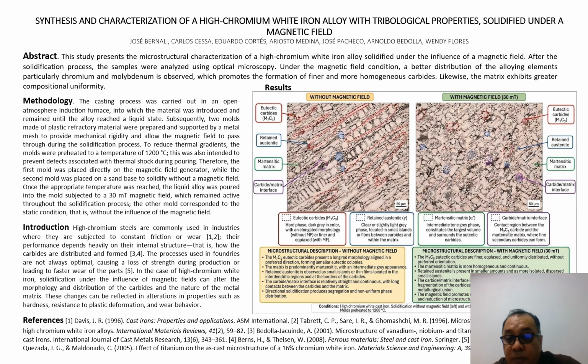Microstructural description with magnetic field. The eutectic carbides are finer, equiaxial, and uniformly distributed with no preferred orientation. The martensitic matrix is more homogeneous and continuous. Retained austenite is present in smaller amounts and more isolated.